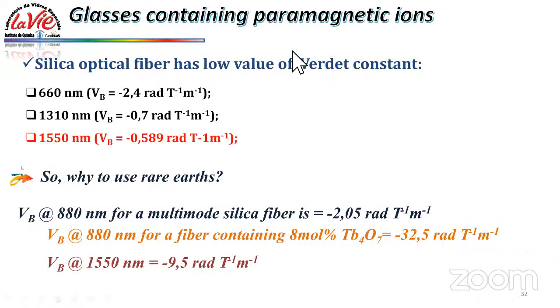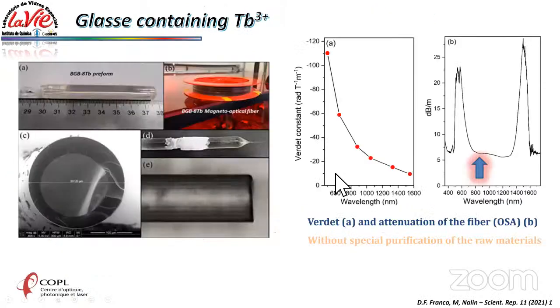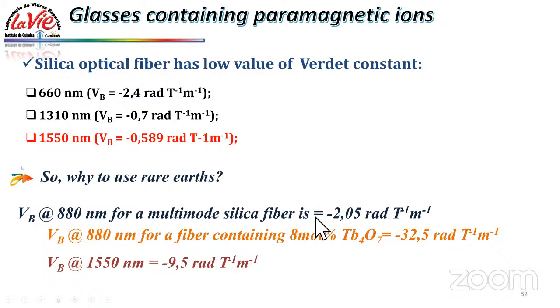So back to this slide, comparing now our results with the silica fiber. We can see here at 880 nanometers the lower attenuation of our fiber. In our case, sorry, this is for silica, it is minus 2.05 rad per Tesla per meter, and for our fiber here, it is minus 32.5. So we have a factor of almost 16 of increase in the Verdet constant in this region. And also for the telecom wavelength, we increase to minus 9.5 rad per Tesla per meter as compared to silica. So this is a very nice result.